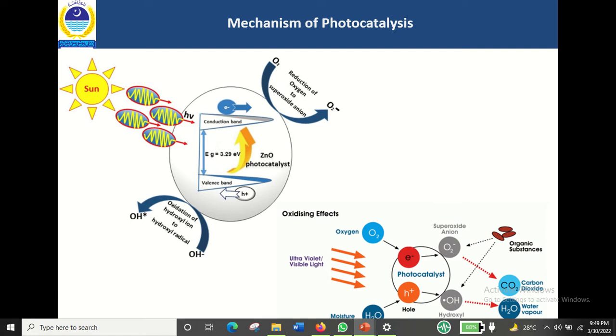So it is necessary to modify this photocatalyst with some suitable dopants to reduce its band gap energy and to enhance its photocatalytic activity. However, there is another issue associated with pristine zinc oxide: it does not respond well to the visible part of the light spectrum when used as a photocatalyst. The photocatalytic activity of the pristine ZnO is also hampered by the rapid recombination of electron-hole pairs, and another factor which reduces photocatalytic activity is photocorrosion.